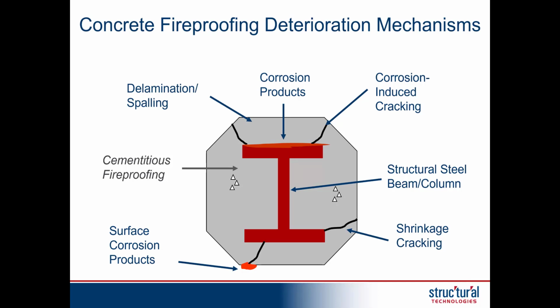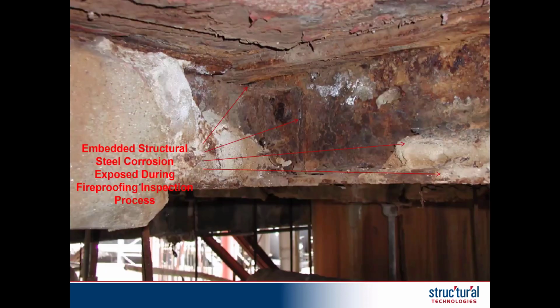But what can happen over time is we get cracking. It's a direct conduit to the outside, allowing moisture and oxygen to get to that embedded structural steel member, and then that results in corrosion. Now, when we say corrosion, this is just a photo from an investigation I did down on the Gulf Coast in the U.S., but this is very typical, where we see the fireproofing having been compromised over many years, lack of maintenance by the in-house maintenance forces because they didn't know what to do or even how to evaluate how bad is bad. But you can see the delaminations.